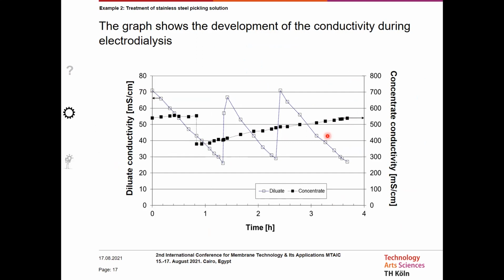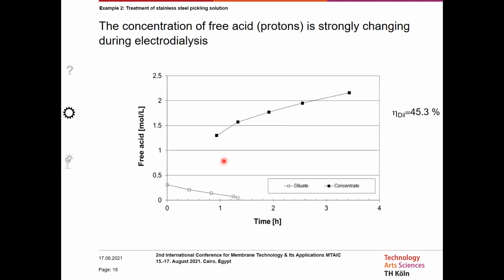We kept the concentrate solution and exchanged the respective dilute solutions once a minimum conductivity was reached. If we go into detail, here is the sketch of the free acid. That means the protons that were transported during this process. And we can see that there was also more or less a linear increase of the proton concentration in the concentrate.